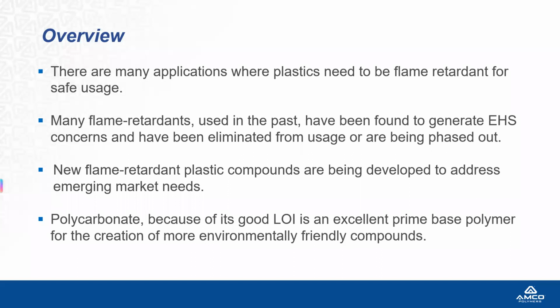Polycarbonate, because of its good limiting oxygen index properties, is a great polymer for FR products. There are other products out there like PEI or PPS that have even higher LOI numbers, but when you look at those products, you're going to see a factor of 2, 3, or 4x in terms of cost. Polycarbonate uses very little flame retardant. Being inherently flame retardant, it uses just a little bit of flame retardant to make it 5VA, and it still maintains its properties, dimensional stability, impact, UV resistance, great creep properties, and it's relatively easy to process.